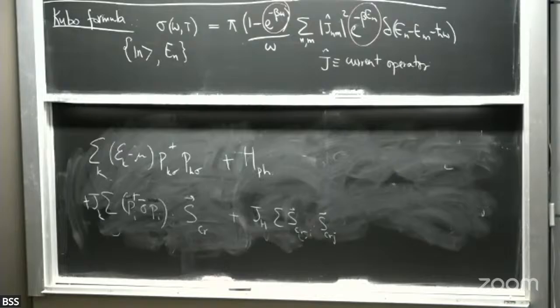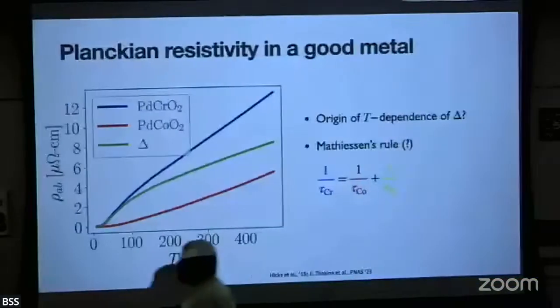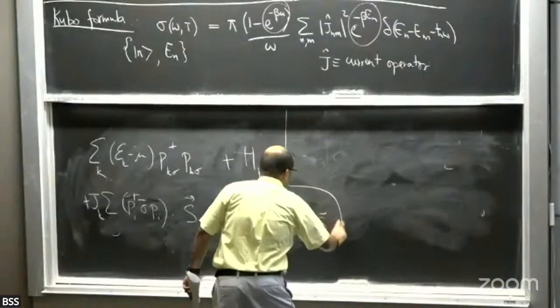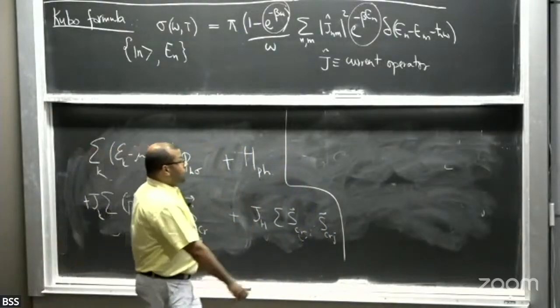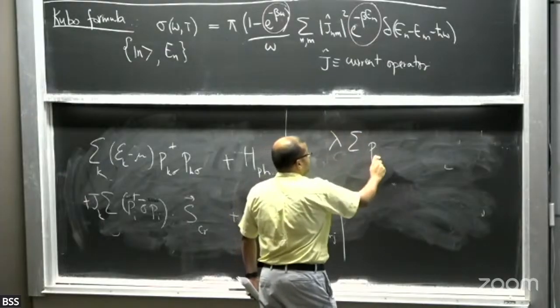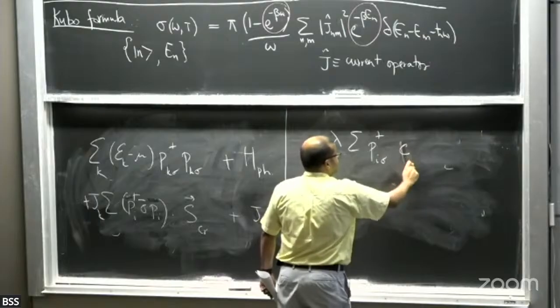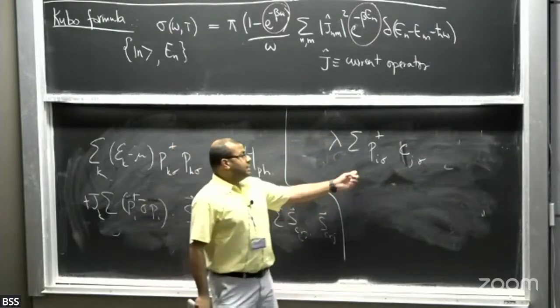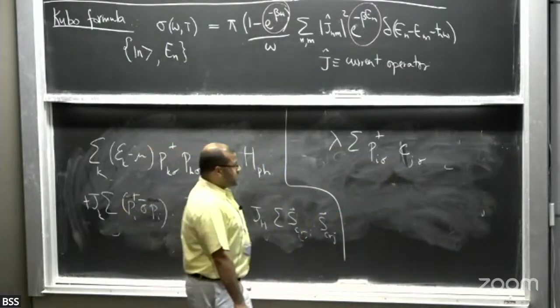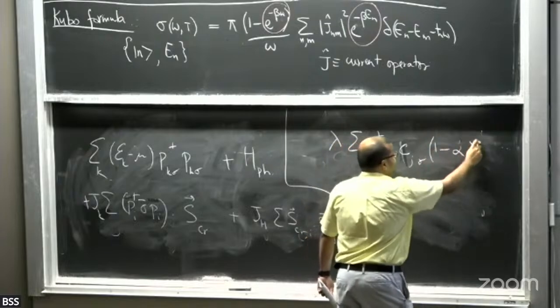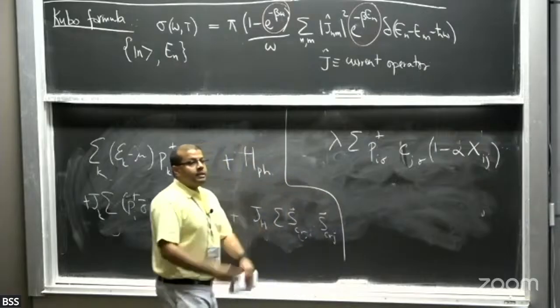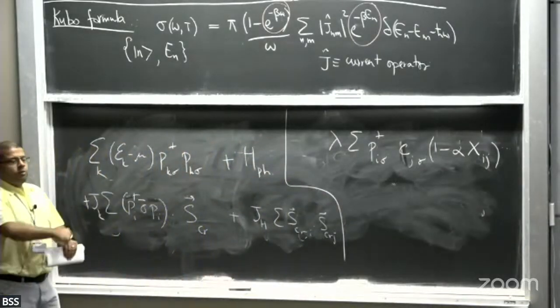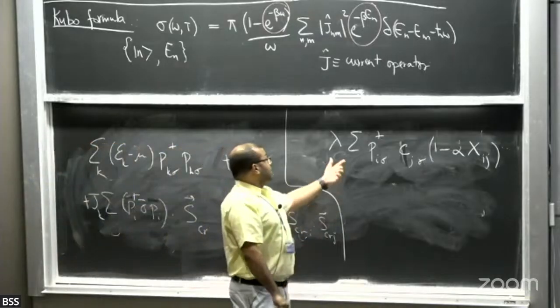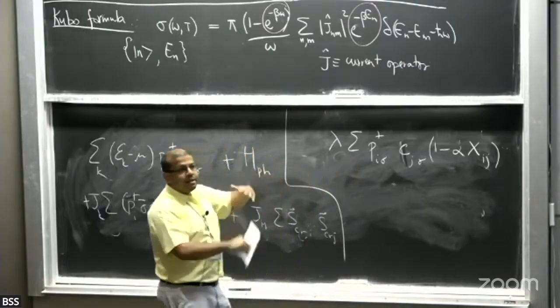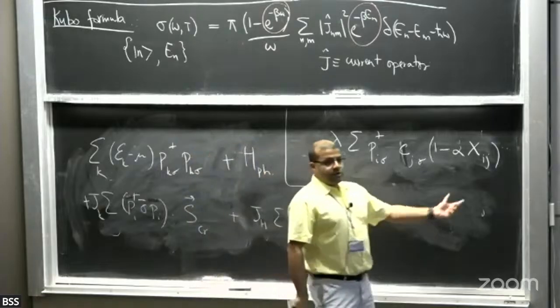Okay, so now the puzzle is where you're getting the excess scattering from. And it's actually connected to something that's quite physical. You have these two things sitting in different layers. So originally, I said, well, there is some tunneling of electrons between the nearest neighbors from the palladium to the chromium. But who said that this can't have additional corrections that depend on the actual displacement between the two layers? When the electrons hop, it's not very rigid. These integrals could themselves depend on the separation, and if these ions are vibrating, it can couple to the phonon displacement.